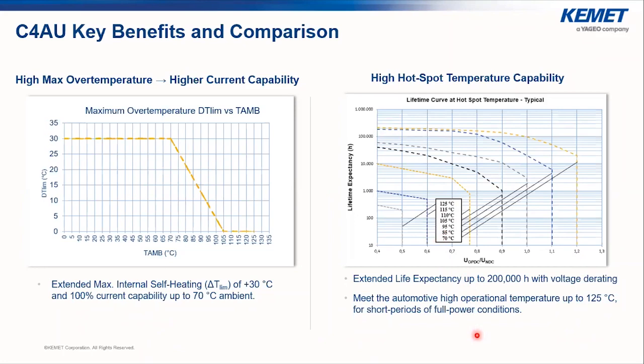So C4AU is the smallest DC-link box design for the most severe harsh environments, for applications with small limited space on the PCB, since the design has the best temperature, humidity, and bias performance at 85 degrees, 85 relative humidity at rated voltage for 1000 hours, where also a high ripple current and high peak current capability is required. On the other hand, its low ESL makes it suitable for frequencies close to those of wide bandgap semiconductor applications.